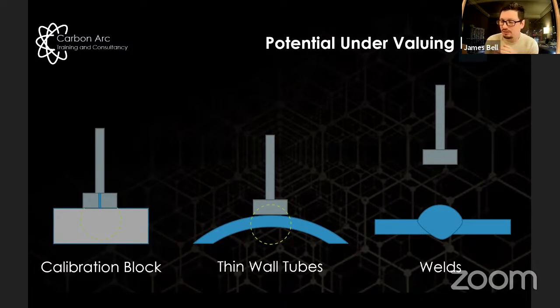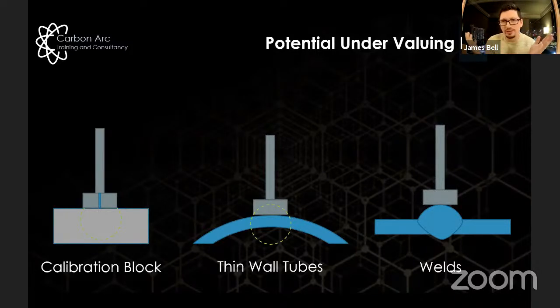Okay, that's a potential. And then what we also started to see was if it was hard to get into and the operator moved the probe left and right as they took the reading, it really threw the data out and to some were passes, some were fails. We saw that if we brought the probe down at one angle, it would fail, but if we moved it, it would become a pass. So it's really starting to say, all right, we've got a fundamental issue with the way this NDT method has been applied.